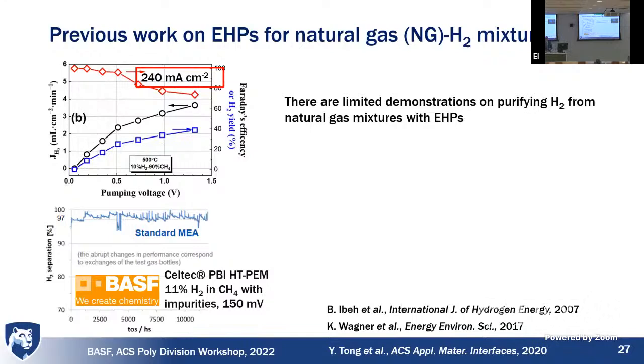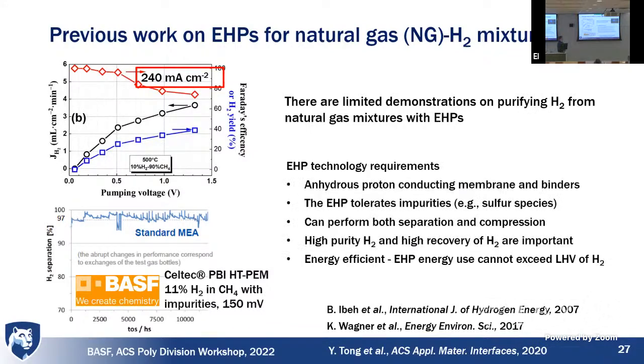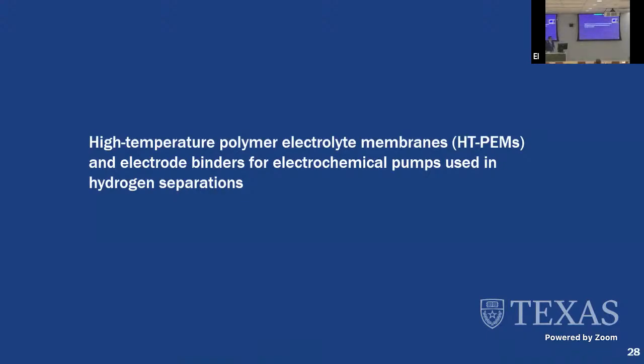But what are the requirements for this technology? The gas mixtures we're putting in the gas pipeline don't have a lot of water content. So normally the membranes for these fuel cells or electrolysis have water with them, and that water is really important for mediating ionic conduction within the membrane. So we need an anhydrous conductor, okay? We need things to tolerate impurities, but most work in this area, if you're going to HT-PEM, have looked at how you purify hydrogen from reformed hydrocarbons with CO. What happens when it's dihydrogen sulfide at 5%? You need to get high purity hydrogen and high recovery. This will be important later on. The nice thing in this pump, not only can you separate the components, but you can compress the hydrogen gas, right? And you need to be energy efficient. You do not want to exceed the lower heating value of hydrogen. So I want to tell you about our work in this area.